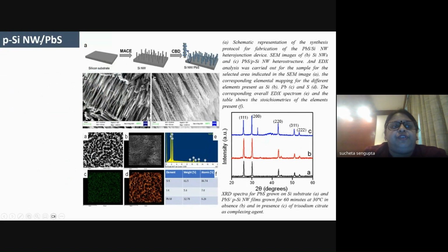Similarly, we tried to do it for the PbS ones. Here we also followed the same approach. We had the silicon substrate, we produced silicon nanowires, and on that we deposited PbS nanostructures to get a uniform coating. These are the same images, and the EDAX shows that PbS is uniformly coated over the silicon nanowires. But here we tried three different conditions. One is over the bare silicon, one is over the silicon nanowires with the PbS, and the last one is where, with the silicon nanowires and PbS, we put a complexing agent, citrate, to control the growth rate.